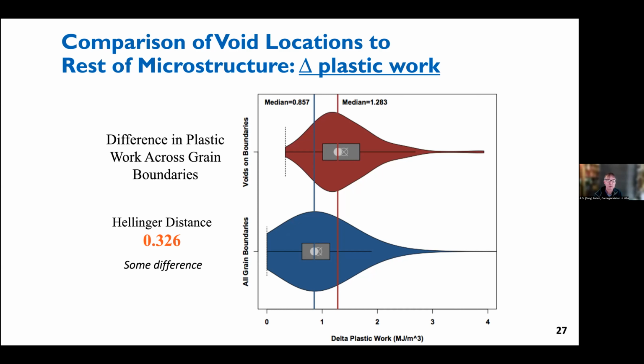But what was interesting was when we talked to other people who, for example, did molecular dynamic simulations, they had, previous to our efforts, found something similar, although they were looking at a very small number of special grain boundaries in their simulations. Whereas I do want to emphasize that this was, in some sense, a statistical result. In other words, looking at an entire collection of voided grain boundaries. And that is basically where we ended up. That was the net result of the effort, and something that I and my colleague Bob Suter would very much like to get back to. The modern tools have improved such a lot. It seems like it would be well worth doing and should have significant impact on damage modeling.